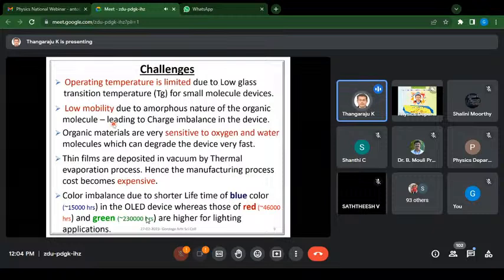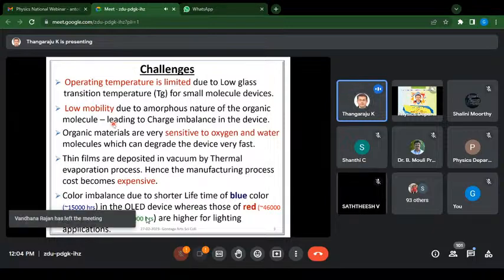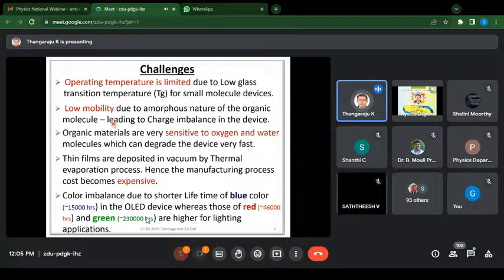And also the organic molecules are very sensitive to oxygen and water. When exposed to oxygen and water in the normal ambient, the organic molecules will get damaged and degraded very fast. To overcome this issue, the commercial organic devices are now being vacuum sealed, and that leads to a very expensive device. And also these organic thin films are currently made by vacuum deposition processes, such as thermal evaporation and other chemical vapor deposition processes, and this should be addressed.